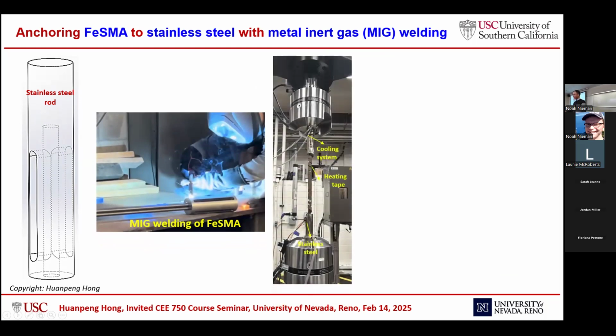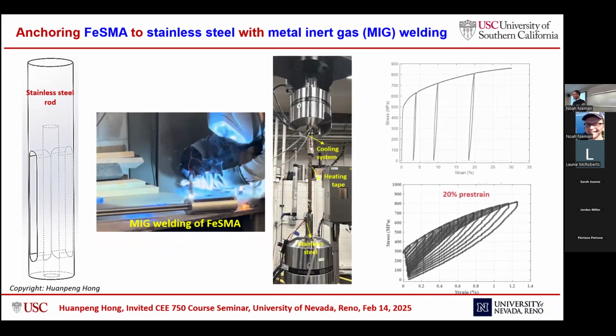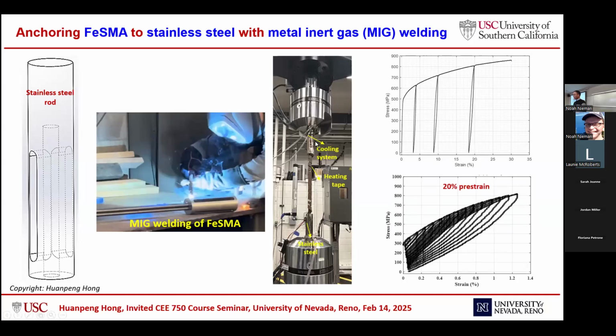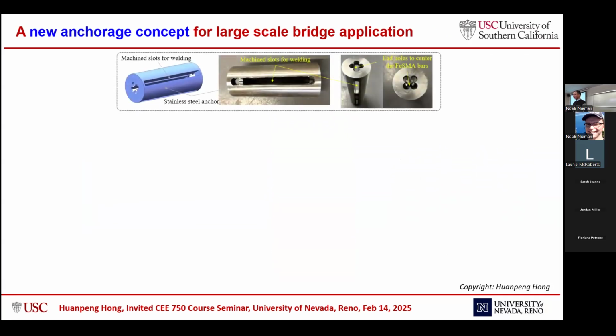To test if this is feasible, we did some material tests, and from the results we found welding this material does not reduce its ductility or its strain recovery capacity. The fracture strain is still as high as 30%, it exhibits around 300 megapascal of recovery stress, and it is still very ductile. Once we got the confirmation from the material test, we developed a new anchorage concept for large-scale bridge applications. Here's the anchorage concept we developed.